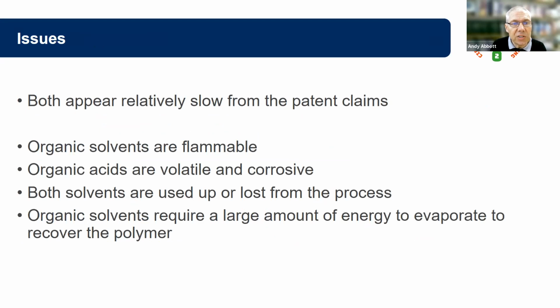What appears from the literature data is that both are relatively slow, and clearly if we're going to have a viable process, it needs to be relatively fast. There are limitations, obviously, with using organic solvents. Clearly the cost is one. The biggest limitation clearly is the flammability. Organic acids tend to be corrosive, but they're also very volatile. And most of these processes that currently are out there work at slightly elevated temperatures. In both processes, there's going to be a significant amount of loss of the solvent from the process. So we need to make sure that we don't lose solvent, to retain circularity. And also with the organic solvents, if we're going to recover the polymers from it, then we need to evaporate off the solvents, and that's clearly going to have a large energy requirement. So there are drawbacks to all of the current technologies.